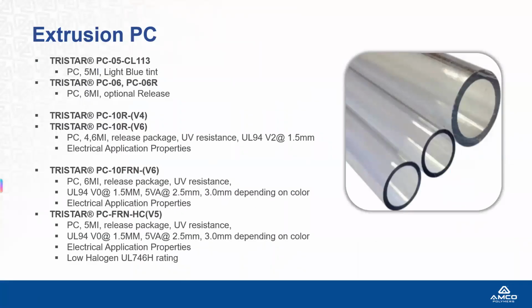Next, I just want to go in a few slides on some new products we have developed, both in brominated, halogenated, and halogen compliant series. So when you look at extrusion, polycarbonate's not like polyethylene where you can get fractional melts. Polycarbonate pretty much bottoms out about 2.5 on your MFI when you're looking at branch materials. So if I were to take that and compound flame retardants in it, the active compounding is going to add roughly 2 to 3 to the melt flow. Flame retardants actually increase your melt flow as well, so that could add another 1 to 2.